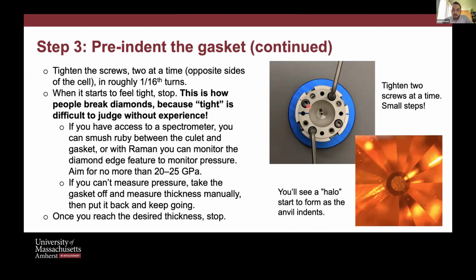And so this is something that you get from experience really, but generally you want to go to pressures of around 20 to 25 if you have a way of measuring the pressure between the culet and the gasket. This is a very rough rule of thumb, and this might actually only apply to 300 micron gaskets, but this is the danger, is that you put too much force, way more than you need, and you've really thinned out the gasket already, and you keep going. Well, when the gasket is really thin, it's not offering any cushion, and so you're essentially pushing diamond into diamond at that point, and that's when things can break.